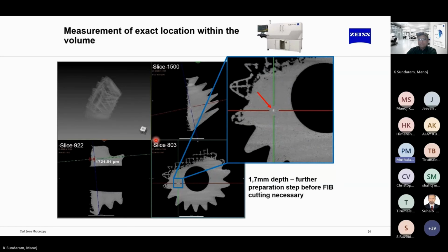When we do manual sample preparation, we introduce artifacts, or by improper sectioning, we may lose the contamination. In this case, we can precisely go up to 1.7 millimeter depth for material removal. Then we will be able to identify the inclusion, and we can do the analysis, imaging, and chemical composition analysis.